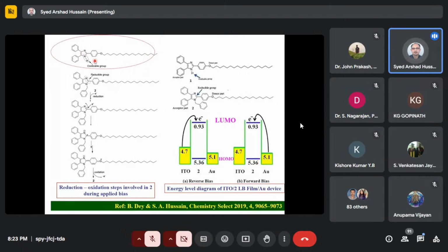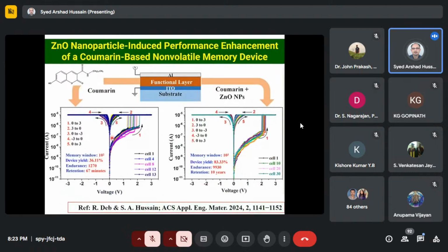Then when we replaced this NH group with a methyl group, the benzyl group, we see that oxidation reduction across this molecule was not possible. Actually, this synthesis was done by our chemistry friends, and I am not much of an expert in this synthesis. Okay, so when we stopped the oxidation reduction across the molecule, we have seen that it's not possible to have the switching. So here the functional group plays an important role.